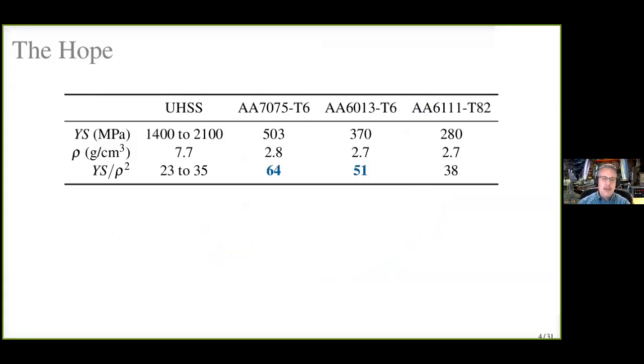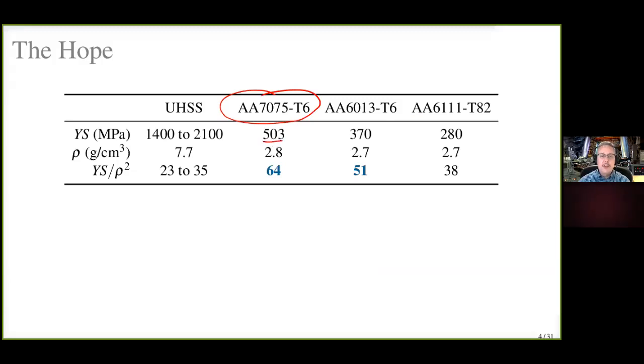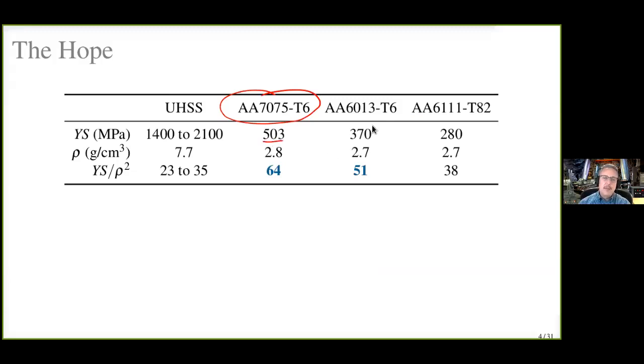Now, the hope is to use something like our AA7075-T6, which is a very high strength aluminum alloy. Now, 6000 series alloys are currently used. 6111-T82 is a current solution that's used in automobile production today. A lot of the outer body panels of the Ford F-150, for example, are made from this material with a kind of a patented heat treatment from Ford. So you can see the strength here is reasonable, but there are other higher strength aluminum alloys we would like to be able to use, particularly 7075 in that B pillar.